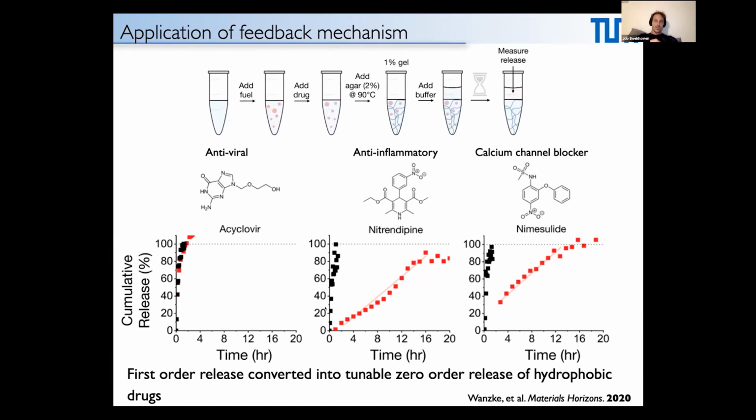We don't do that with the oil droplets. It releases the first order kinetics within an hour. And now we're just sitting there almost 24 hours and we have this linear decay. That means that as a patient, if you apply such a hydrogel to your skin or whatsoever, it releases the same amount of drugs every hour for 24 hours.